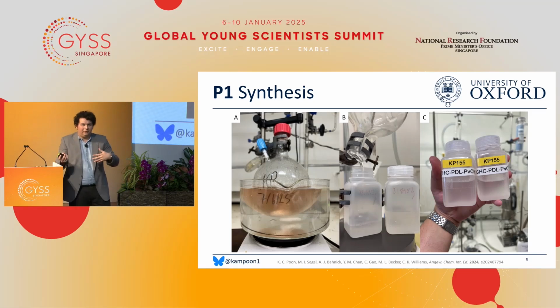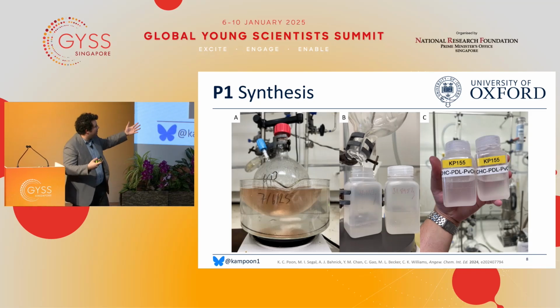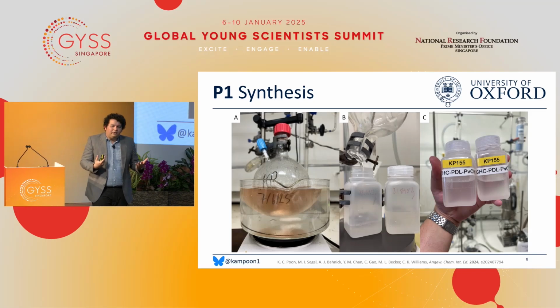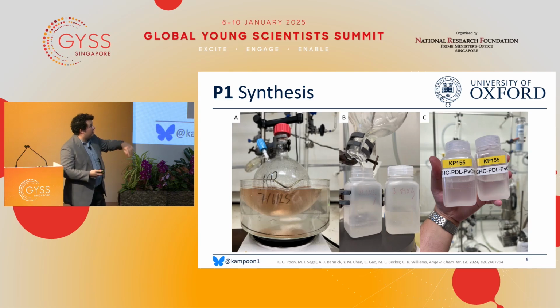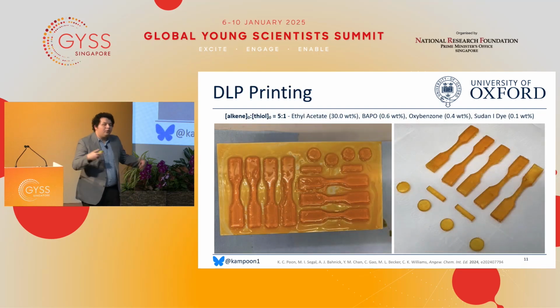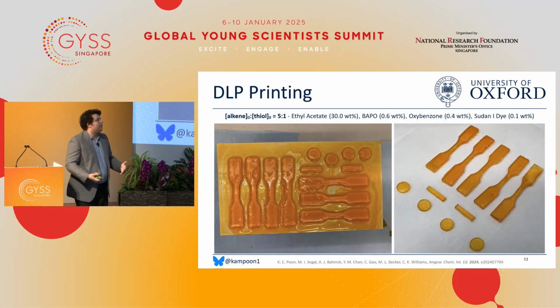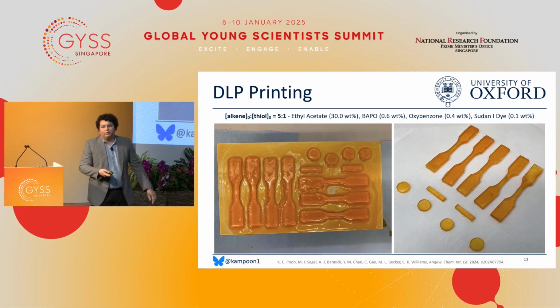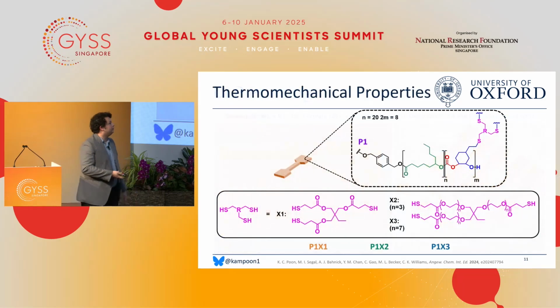So to turn these ChemDraws into reality, I made this. For this kind of printing, you need quite a lot of material, so we produced 204 grams of it. So here's the synthesis. You can see it's a lovely colorless liquid. And then through some optimization, we were able to print this. And here is the first successful print, which was a very exciting day. And you can see we've just produced some very simple specimens for thermomechanical testing.